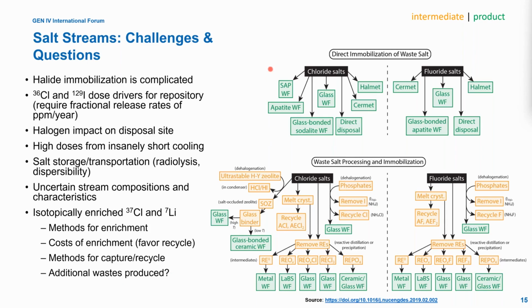For the different salts, there are some options that have been demonstrated for chloride salts where the full salt could be immobilized or processed into some sort of a stable waste form. Things like apatite, things like sodalite, these are minerals that I'll talk about a little bit later, where the halides are actually immobilized inside the crystalline lattice. And then those can be encapsulated with a glass phase that helps prevent leaching during chemical durability testing. There's things like halide metal composites or halmets. There's ceramic metal composites called cermets. And a lot of this work has been done with chlorides, but very little has been done with fluoride salts. So more work is needed in that area.